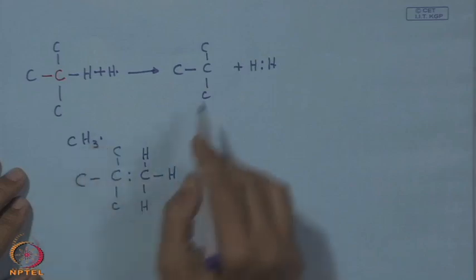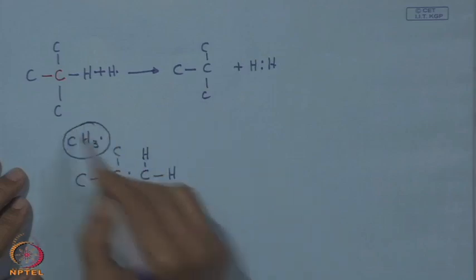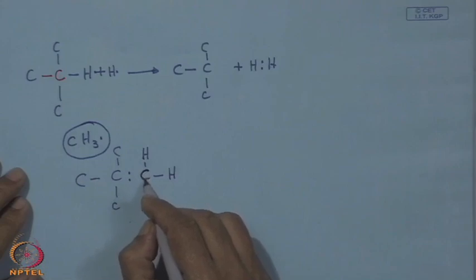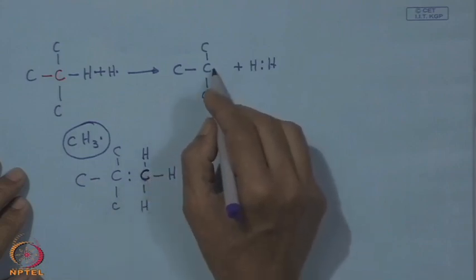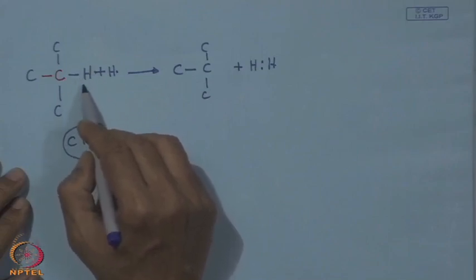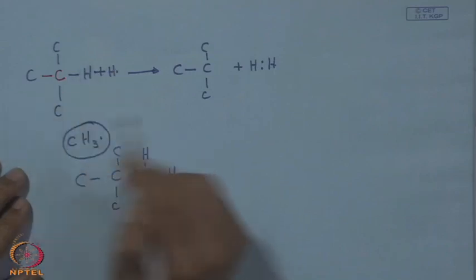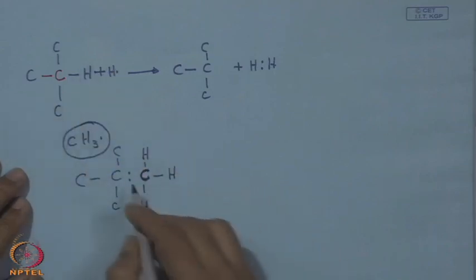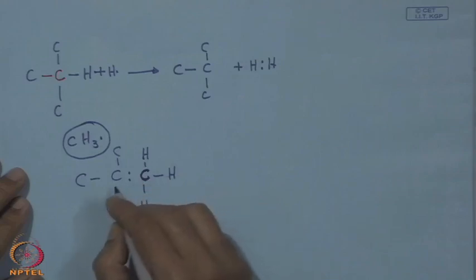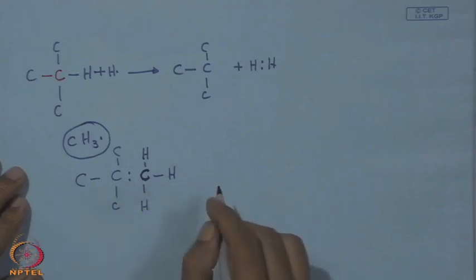So, the carbon from methyl radical is occupying this position which is left vacant because of the stripping of this hydrogen, which forms a dangling bond at the top, and this is removed by this atomic hydrogen. So, what we see now, and this process will keep on going, it will keep on repeating.